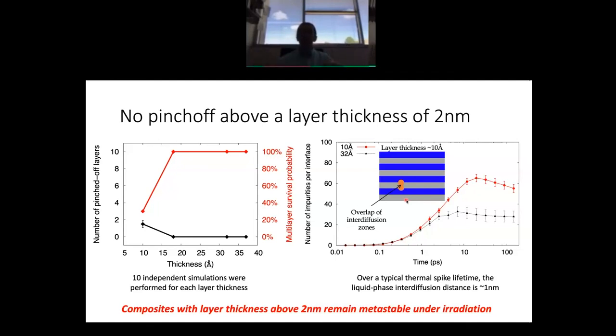And then during subsequent solid phase demixing, those layers are just going to return back to their original state. So the conclusion here is that composites with layer thicknesses above 2 nanometers remain metastable under radiation. Good news. Okay? So that was vignette number 2.